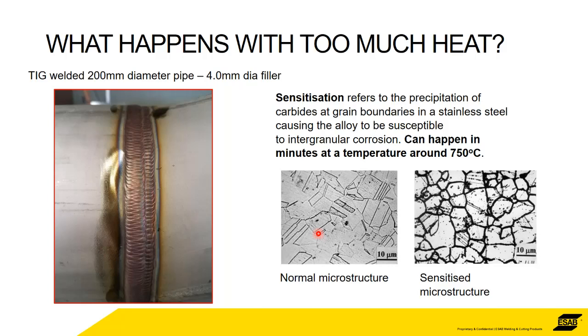So this is an example of a stainless steel pipe that, on the face of it, the weld looks pretty good. There may be a bit of heat tint, but you don't really know that from a photograph. However, in service, this construction lasted about a month. It's stainless steel. It should have lasted years. And when the weld was microsectioned and looked at under a microscope, it was very, very obvious that too much heat had been put into this TIG weld.